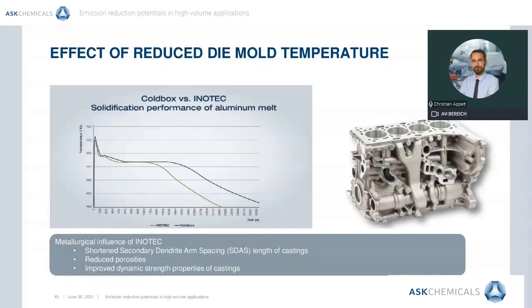An additional advantage of the inorganic binder technology, Inotec, is embedded in its technological influence on the metallurgic structure of the casted aluminum parts. The metallurgic property of secondary dendritic arm spacing is mainly influenced by solidification. Thus, faster solidification leads to lower SDAS values and castings with higher mechanical strength. Lower permanent die mold temperatures in case of Inotec already provide faster solidification. But the residual water of the inorganic binder bridge further withdraws energy from the liquid aluminum melt for evaporation, leading to an add-on effect on solidification.